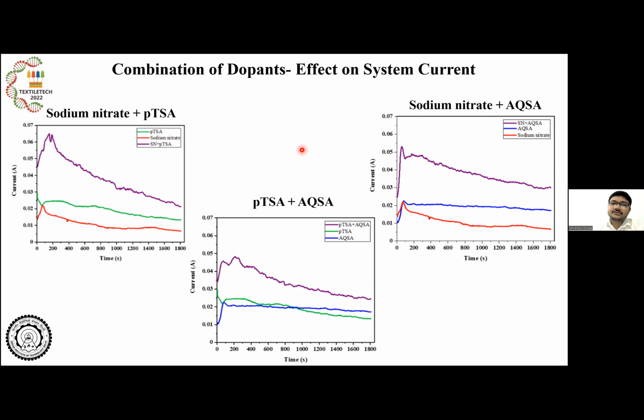Since sodium nitrate was allowing higher current to pass through the system, it was combined with different dopants, like PTSA and AQSA, which are known to be good dopants. The combinations were sodium nitrate with PTSA, sodium nitrate with AQSA, and PTSA plus AQSA. In this case, it was observed that the highest current was there when sodium nitrate was combined with PTSA in the electrochemical system. This current is not just the algebraic sum; it is higher than the summation of these two currents.